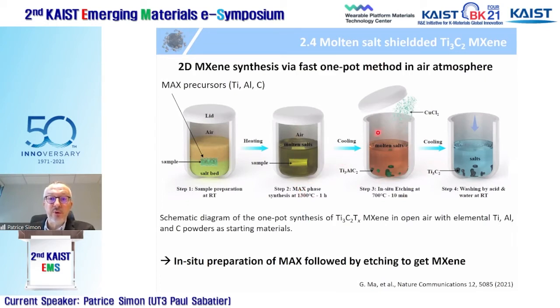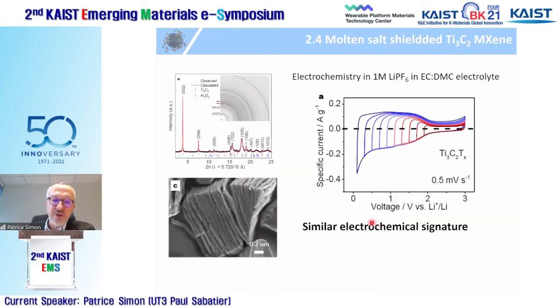And then you open your crucible and you add the Lewis acid etchant, copper chloride, to etch in situ the MAX phase that you prepared in situ during the molten salt synthesis. And then at the end, you recover your Ti3C2 MXene layer powder that you need to wash to remove the copper. By doing that, you can in situ prepare the MAX followed by in situ etching of the MXene. And just to show you that by doing that, you can prepare MAX phase in situ and then finally MXene with also the same efficiency. You have MXene from the XRD pattern, the exactly same electrochemical signature.